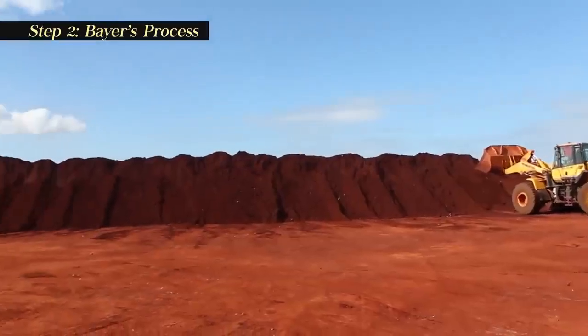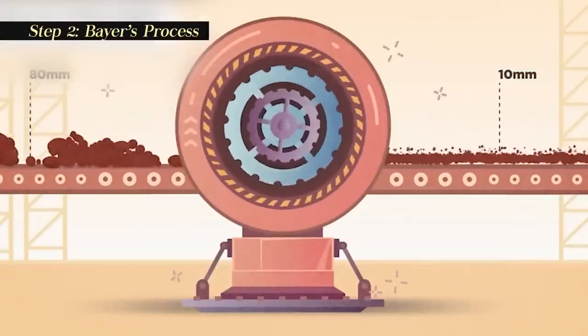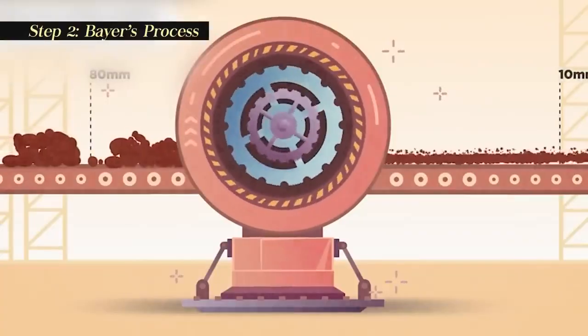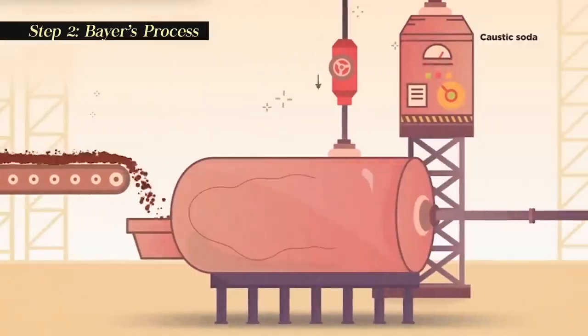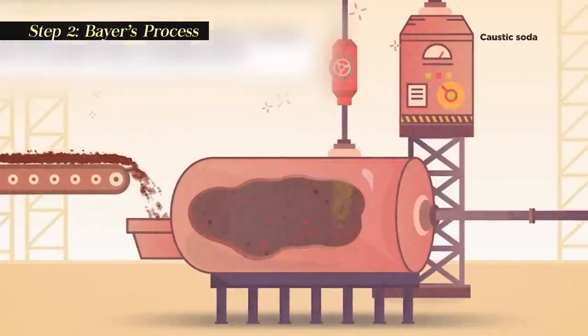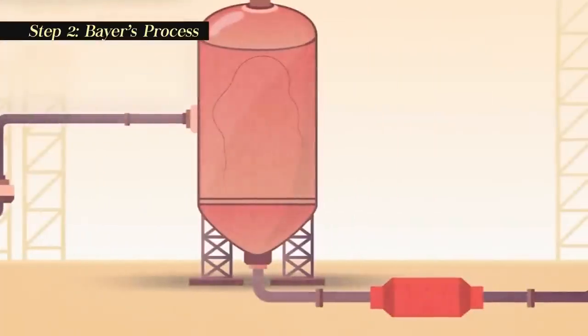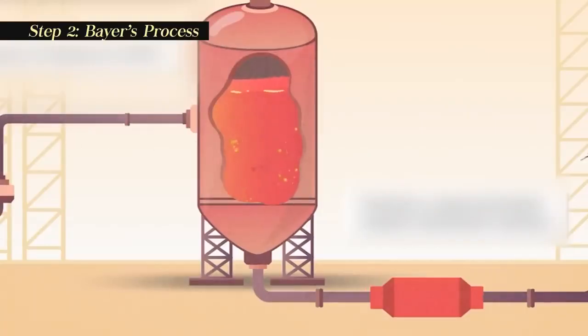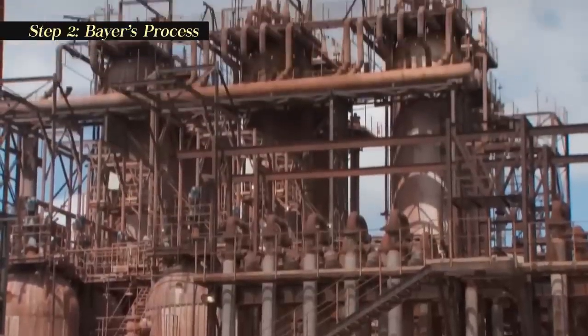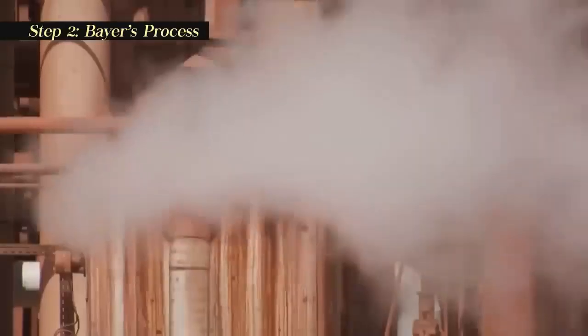The refining process involves several steps. First, the bauxite ore is mechanically crushed. Then, the crushed ore is mixed with caustic soda and processed in a grinding mill to produce a slurry, a watery suspension containing very fine particles of ore. The slurry is pumped into a digester, a tank that functions like a pressure cooker. The slurry is heated to 230 to 520 degrees Fahrenheit, 110 to 271 degrees Celsius, under a pressure of 50 pounds per inch squared, 340 kPa. These conditions are maintained for a time ranging from half an hour to several hours.